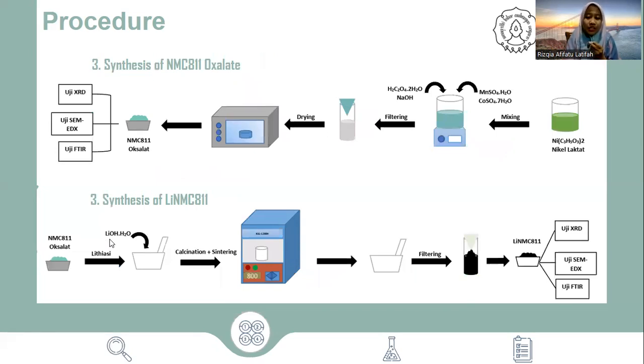And then the leaching solution is heated and stirred. Manganese sulfate and cobalt sulfate are added to the solution according to the calculation. Then dissolved oxalic acid was added to the manganese and cobalt leaching filtered mixture. And then sodium hydroxide was added until the pH is 2. After the temperature reached 80 degrees Celsius, the process is carried out for 2 hours. Then the precipitate was washed until neutral, filtered, and dried.